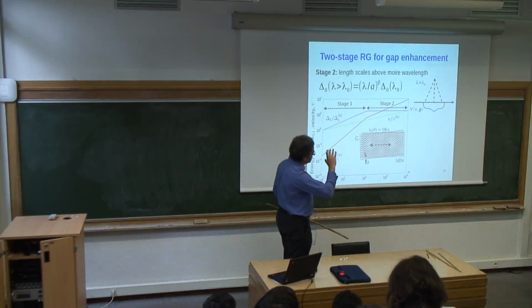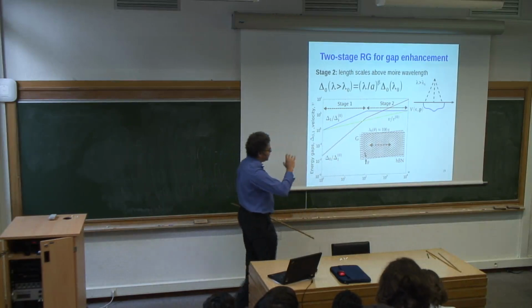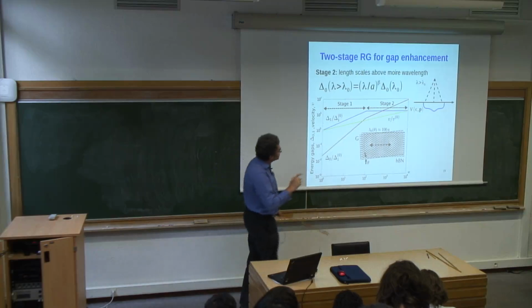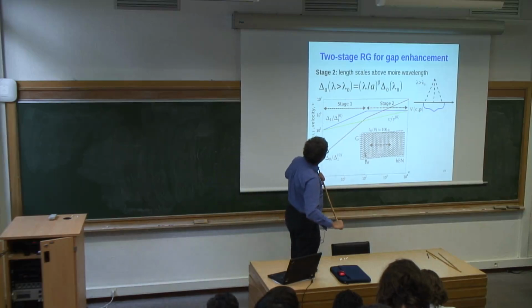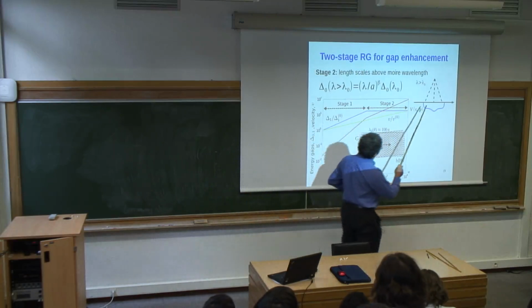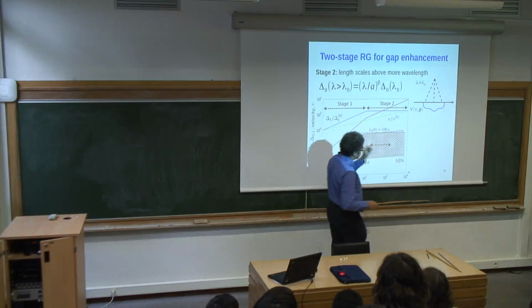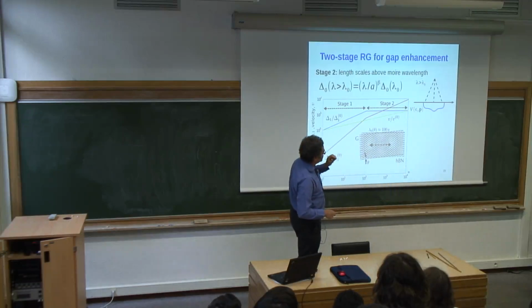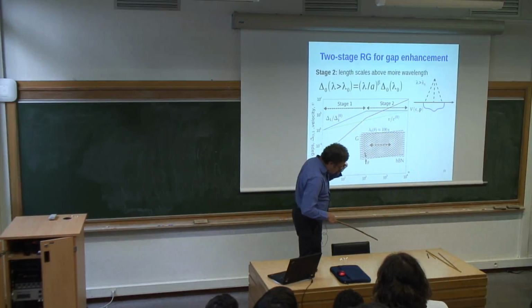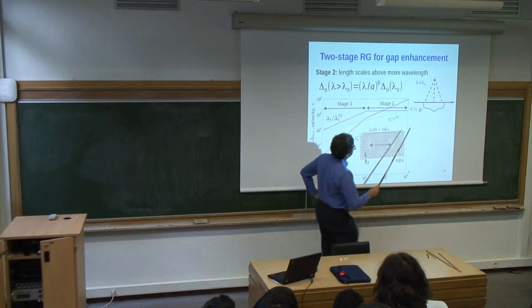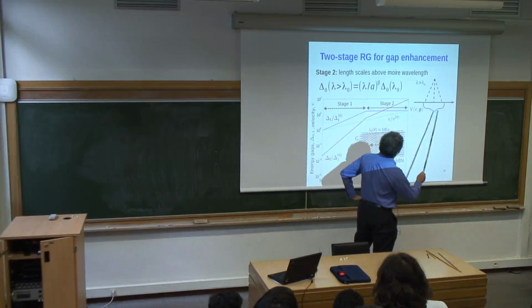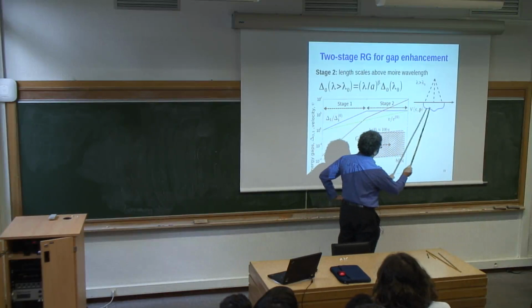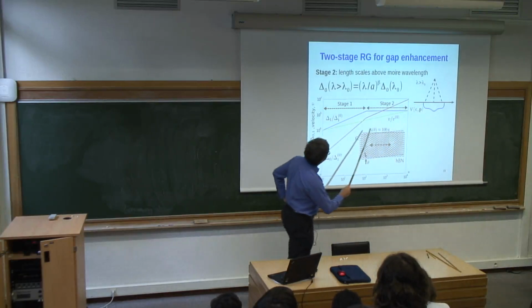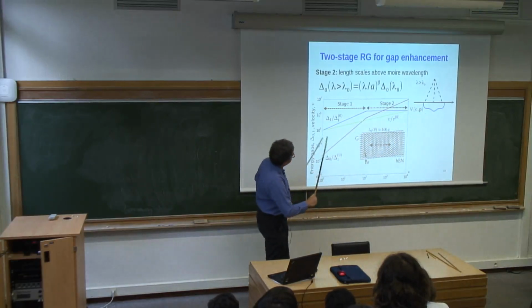your particle energy becomes smaller than your particle momentum becomes smaller than the Bragg scattering momentum, and so you have to treat this perturbation as a zero Bragg scattering perturbation, as the spatial uniform mass term. And so then renormalization proceeds in a slightly different way, in this more conventional way that we mentioned, and then you have to, so there are 2 stages of RG.